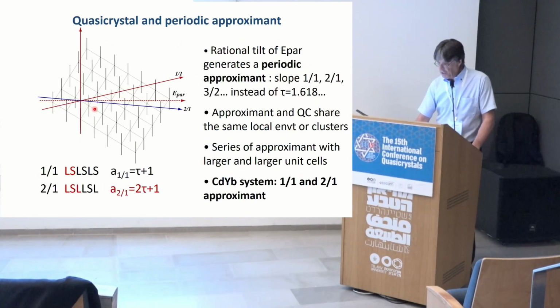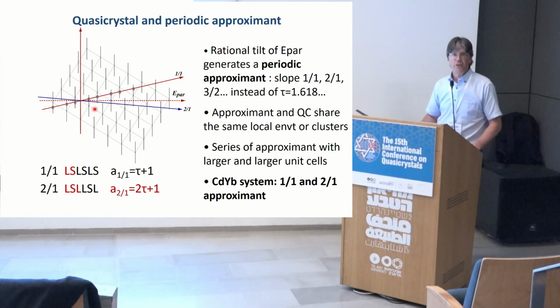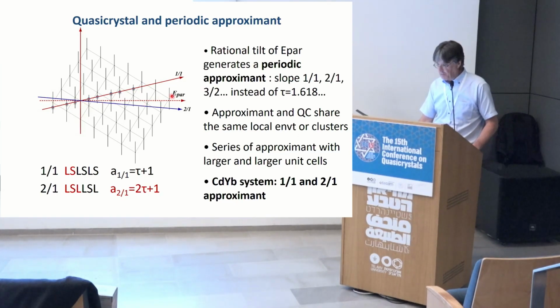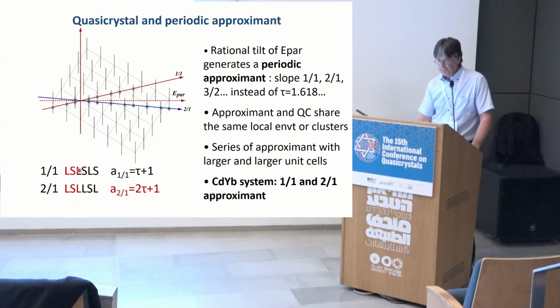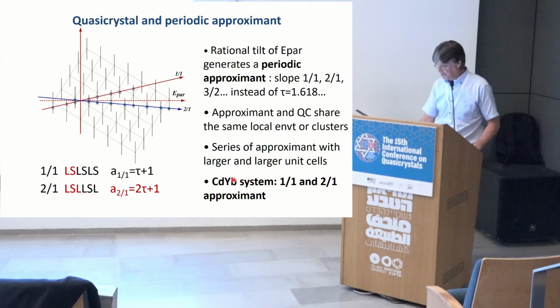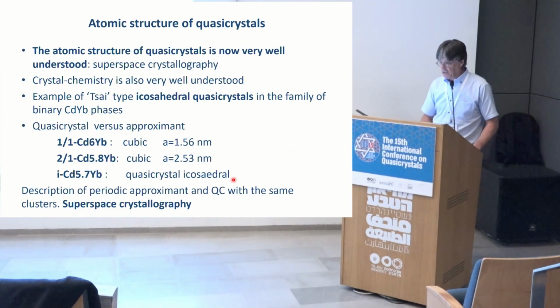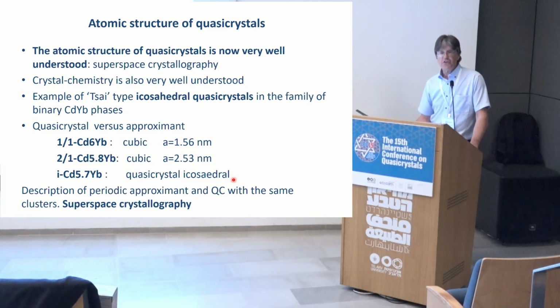And finally, we have a periodic approximant, which was predicted by the theory and which occurred also in practice. The way it can be seen in this high dimensional space is shown here. If instead of this line, which is irrational with respect to the underlying square lattice, we take a rational approximant, 1-1 or 2-1, we have a periodic distribution of the tile, and this is what is observed experimentally in this cadmium-ytterbium system. So I will now illustrate that on the structure for which we have the most detail, which is